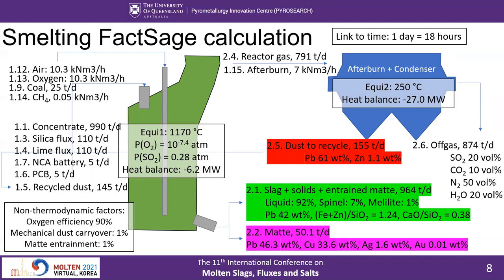Higher dust turnover is expected when the furnace operates under more reducing conditions. Also, liquid slag contains solid phases — spinel and melilite — meaning it operates below liquidus. Lower temperature and saturation with solids may slow down the corrosion of refractories, but the furnace needs high agitation to prevent the formation of accretions. The percent solids need to be controlled below a certain level to allow efficient skimming of slag. Thus, in addition to good thermodynamic predictions, advanced temperature measurements and flexible fluxing control may be needed to operate the furnace safely under liquidus.